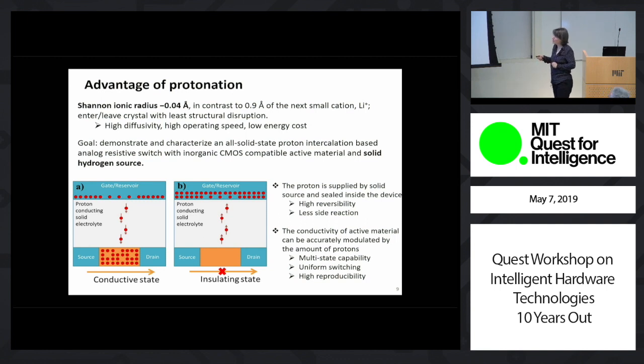Okay? So the idea would be we use a solid hydrogen reservoir and electrochemically pull hydrogen out of this reservoir through a proton-conducting electrolyte into a proton-sensitive active material or channel material whose conductivity can be fine-tuned by controlling the proton content in that layer. Okay? And similarly, electrochemically, you can pull them out. And in this way, we can obtain multi-state capability and rather uniform switching rather than filamentary switching.